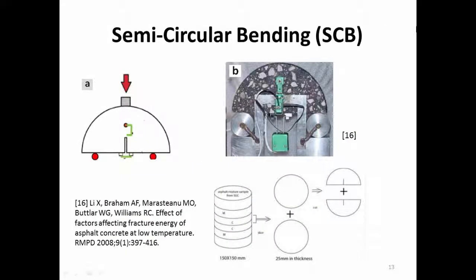So then people said, okay, we have cylindrical samples, and we don't want to chop them too much. So we came up with this half disc. It's a semicircular bending test. They get one specimen either from the lab or from the field, and chop it into different layers. Each of them is cut into halves, and then each can be fabricated into two SCB specimens. So this is easier than the rectangular shape, right? So that has been used for many years.